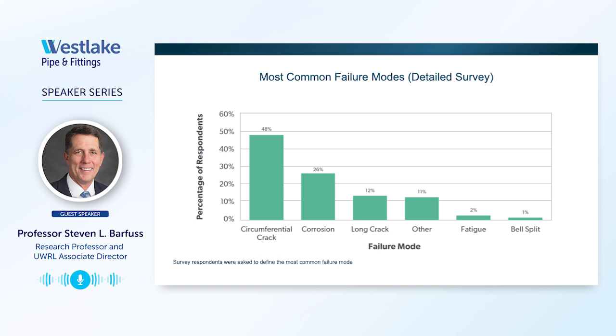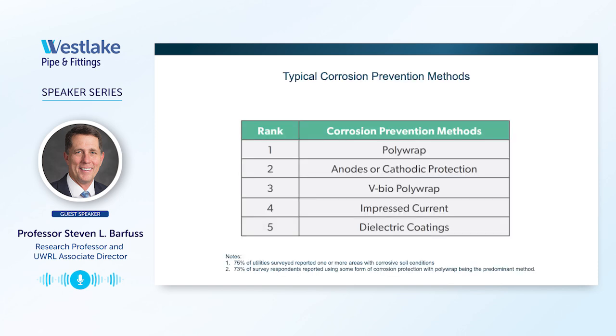We ask about common failure modes. Here's how it was reported for how pipes fail. Circumferential crack and corrosion being the most common failure modes. We ask about corrosion prevention methods, polywrap and cathodic protection being the most common in terms of how iron-based pipes are protected. Down here, I have a note: 75% of utilities surveyed reported one or more areas in their system that have corrosive soil conditions, and 73% reported some kind of corrosion protection that's used in their system.